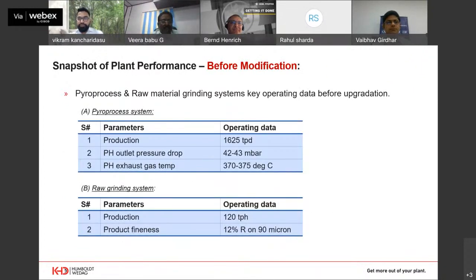You see the key data before the modification. The pyroprocess line was operating at 1625 TPD with a 42 to 43 millibar pressure drop at the preheater outlet, and a temperature of 370 to 375 degrees for a 5-stage preheater. And in the raw grinding system, a roller press finish mode circuit was there, but of old generation. It was giving 120 TPH at a 12% residue on 90 micron.